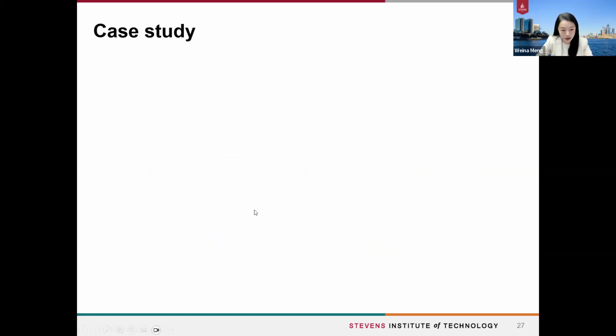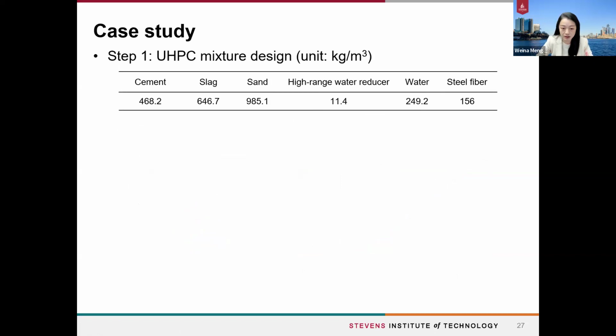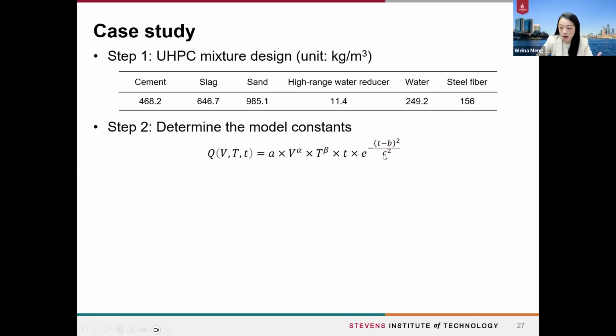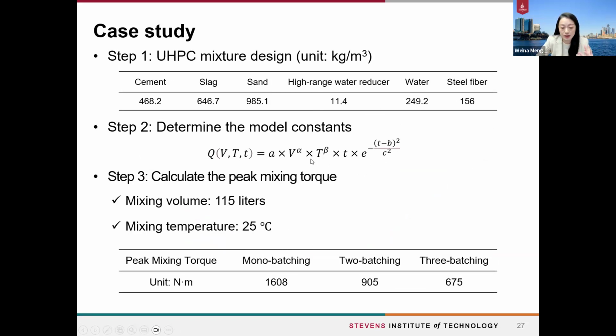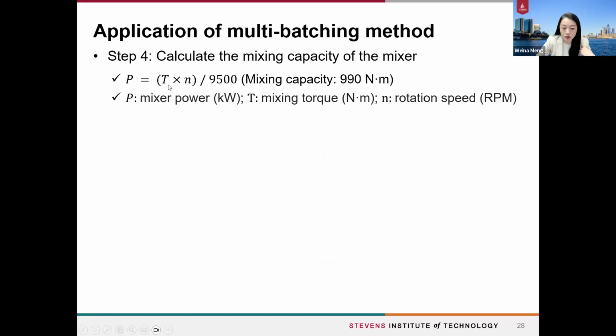So here shows the case study. If you have a certain UHPC mixture design, the first thing you should do is to determine the model constants by conducting some small batches of UHPC. And once you determine the constants, and given the volumes that you target to mix and the mixing temperatures for construction, you can determine the mixing torque for mono batching, 2 batching, or 3 batches. And after that, given the mixer you have, you may have a normal mixer, pan mixer, or high shear mixer, whatever the mixer you have, you can calculate the mixing capacity of the mixer.